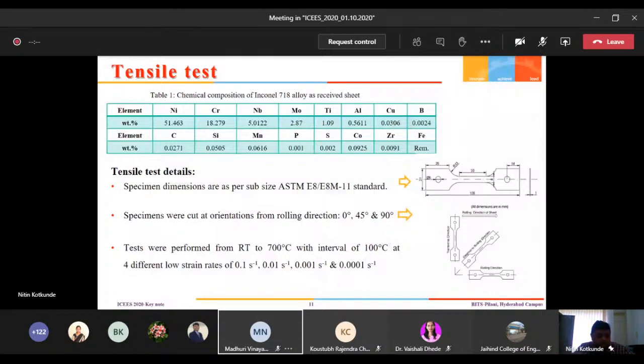So a sophisticated special purpose uniaxial machine which has this kind of arrangement should be used to test it, because all the material models are based on the input of strain rate, strain and temperature. So we have tested Inconel 718 from room temperature to 700 degrees at an interval of 100 degrees with 4 different slow strain rates. Strain rate ranges are given here.